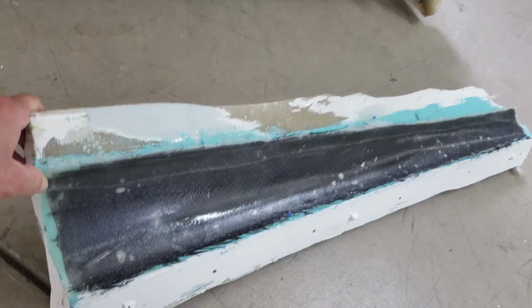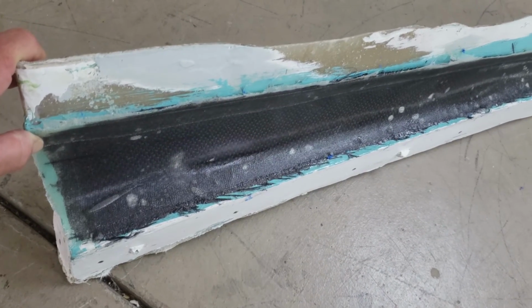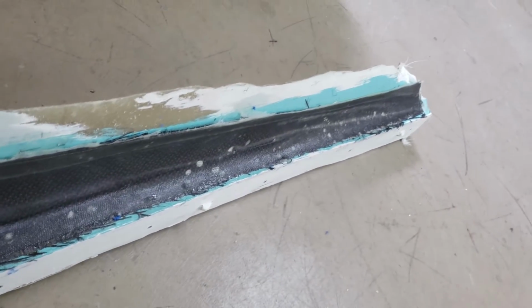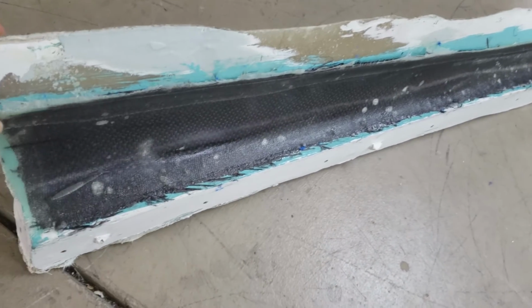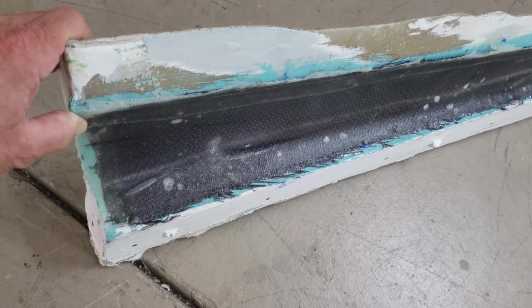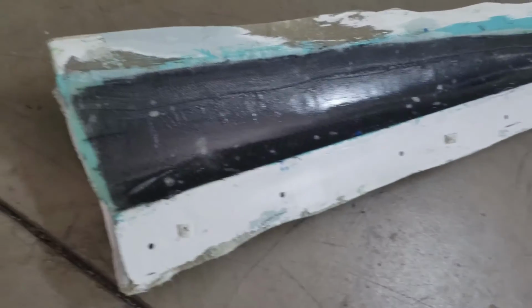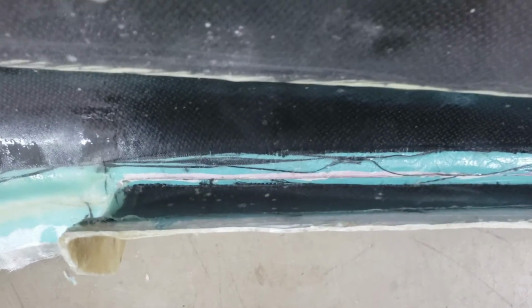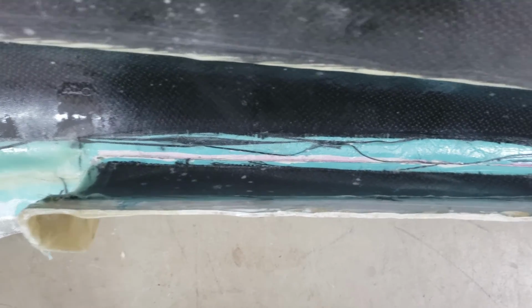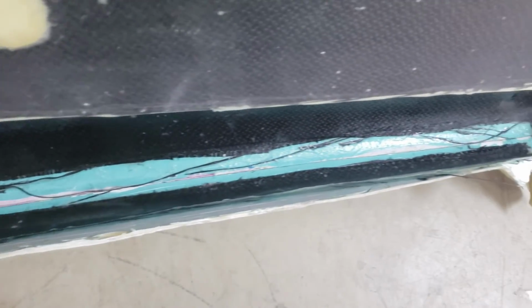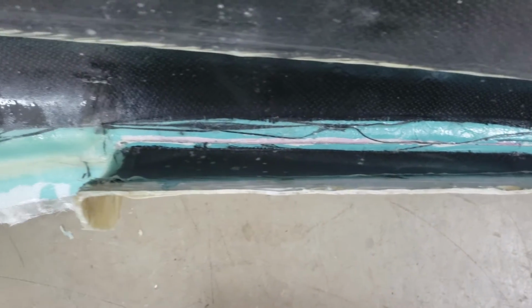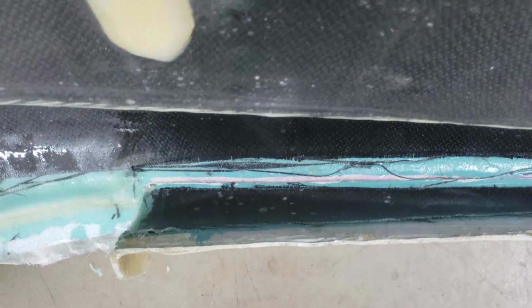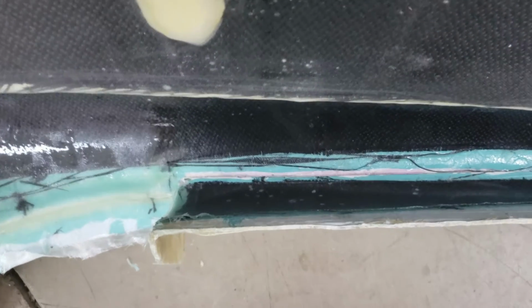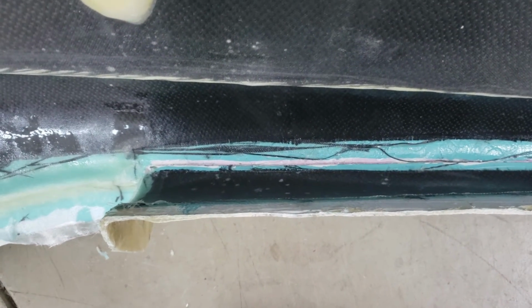It's been laid in, but you can also see that I sort of held back on the carbon fiber and the fiberglass that are in there, so you can still see the green gel coat. And this is why. When you bolt the two pieces together, it looks like this. So I've got a gap down in there. You can see the gel coat as well as the crack where the two pieces meet. Now it's a pretty tight crack. It may not look that way in this picture, but it's a pretty tight fit there.